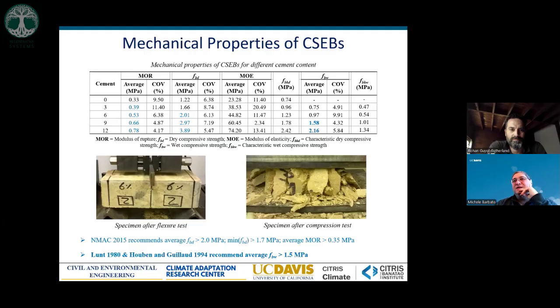But then when we started looking at the wet compressive strength, which needs to be above 1.5 megapascal to ensure proper durability of the material, we had to increase our amount of cement to 9 and 12%. And so these two levels are the ones that we used for our further investigation of the mechanical properties of the entire structure, not only of the components.